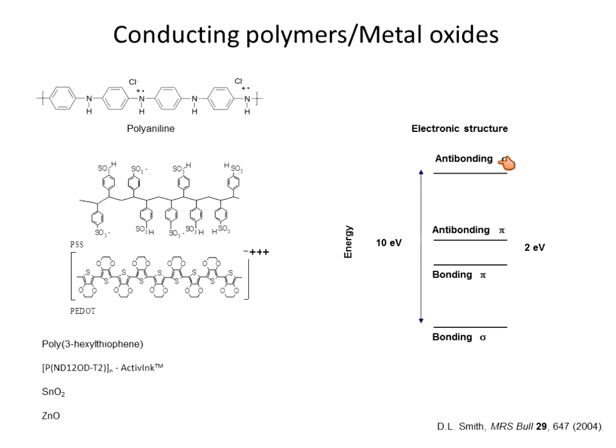The interesting thing in these polymers is that any defect that you would find along these polymer chains, any of these defect states, would lie in the bonding or anti-bonding orbitals' energy levels, and so they do not affect the electronic properties of these conducting polymers. That is one reason why you can make reasonably good devices out of them under ordinary lab conditions. If you were to work with silicon, you would have to use a clean room, for example. So here are some of the polymers that we work with. We have synthesized some of these, but typically if they are available commercially, we just purchase them and use them in our lab.